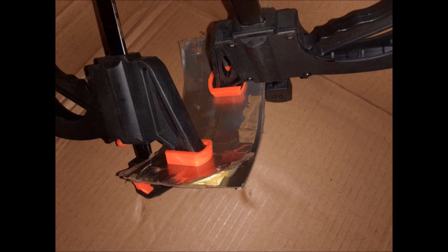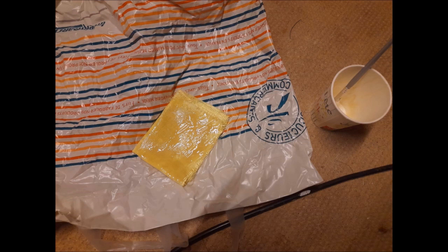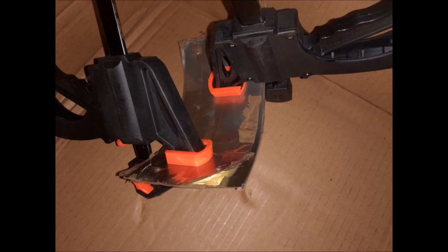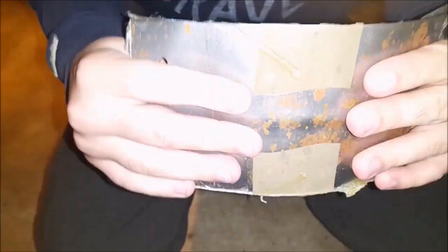For the aramid epoxy lamination, I simply prepared 2 thin pieces of sheet metal that I bent with the correct curvature and covered both with tape, as epoxy will stick less to it than to the raw metal. You can use plastic shopping bags as well, as epoxy sticks far less to them than to most other materials. And then I did a classic lamination, where I laid each layer of aramid down on the lower metal sheet, covered the aramid in epoxy, added the next layer of aramid, and so on, until the 4 layers of aramid were placed and soaked with epoxy resin. Then I put the second sheet of metal above it, sandwiching the aramid epoxy between 2 sheets of metal, and used clamps to compress and keep the whole thing under pressure for multiple days. Once the epoxy dried up and cured, I took the clamps and the sheets of metal apart and made the next lamination, and so on until I had 1 aramid epoxy laminated piece for each pad.